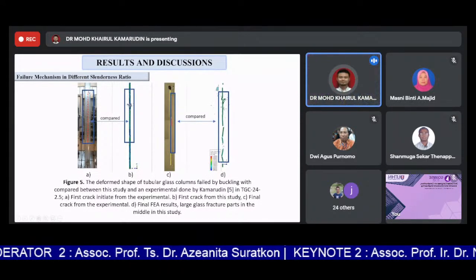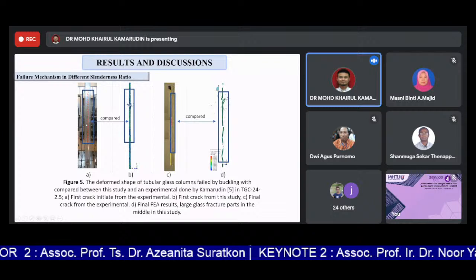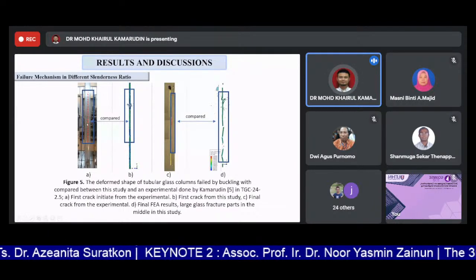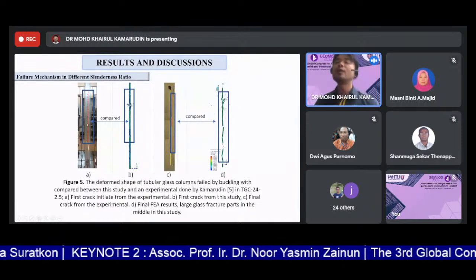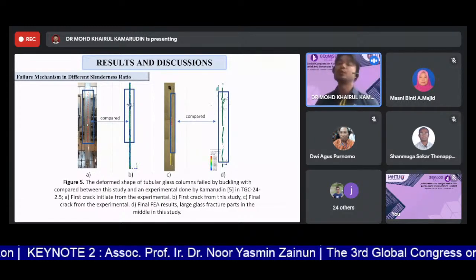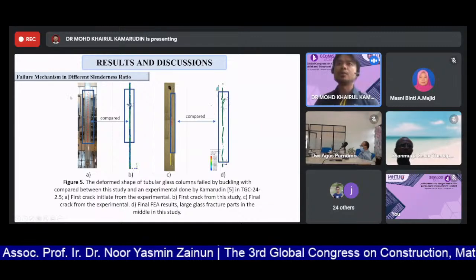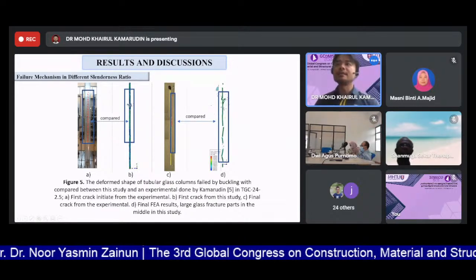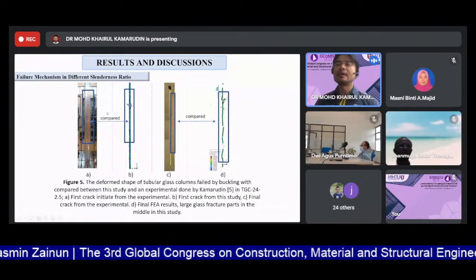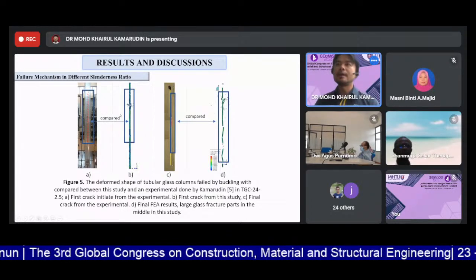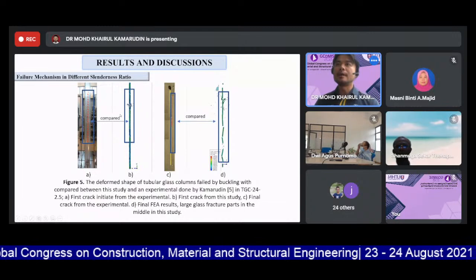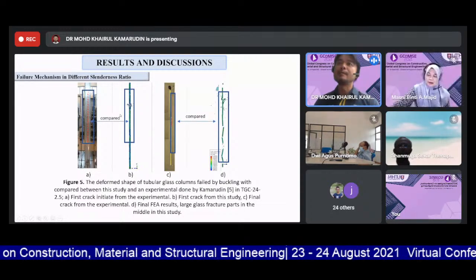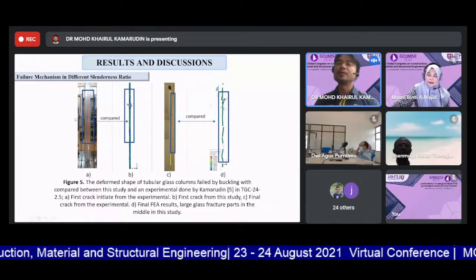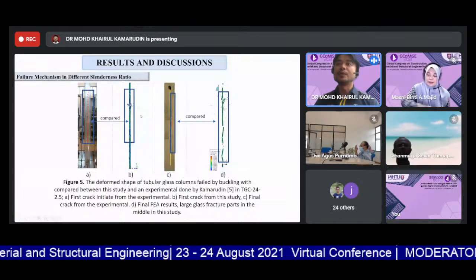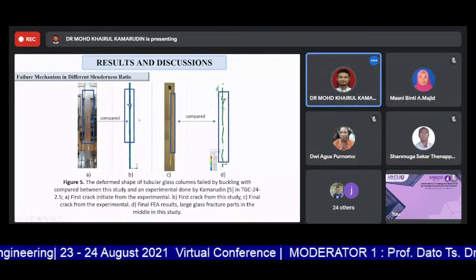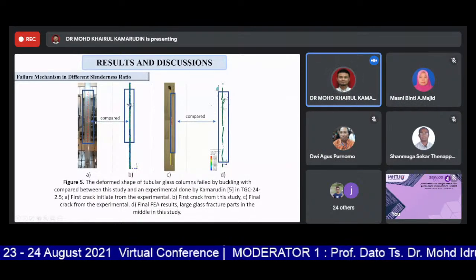Experimental work. This is the size of 24 diameter glass tube with a 2.5 wall thickness. The glass is expected to buckle, and then when we conduct the analysis, it buckles at the midsection of the columns, and we tend to see this as a comparable result between the FE as well as the experimental work.